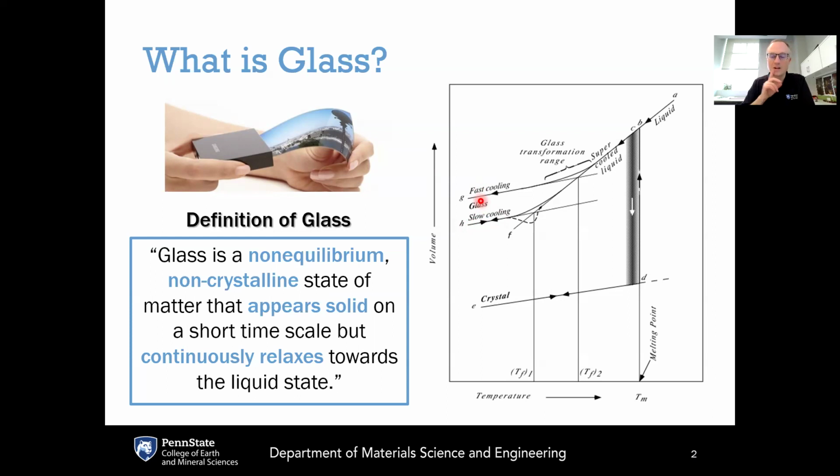So this is very interesting. And it also means that we need to have an additional thermodynamic parameter to describe the state of the glass. It's not like a crystal, right? With a crystal, if you're in equilibrium, the entire state of the crystal is defined by its chemistry and its temperature and its pressure, assuming that you're at equilibrium. There's only one possible state that it could be in. With the glass, there are an infinite number of possible states that the glass could be in, depending upon the different cooling pathways that you could take.